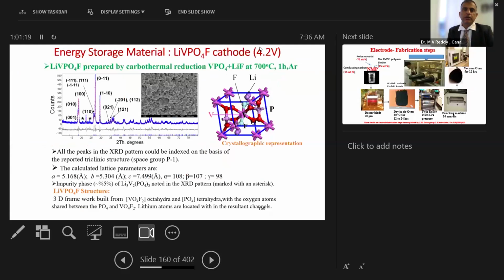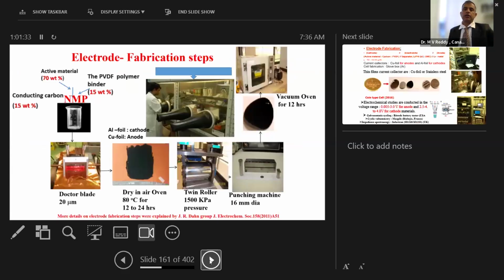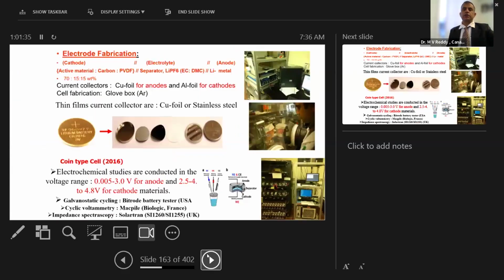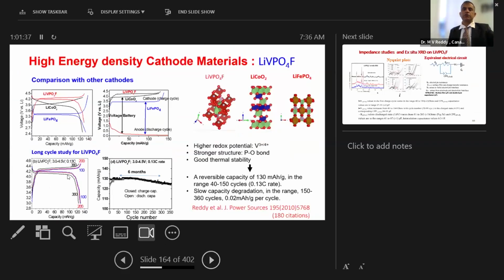So typically you get a 4.2 volt cathode material. I told you that there is VPO4 LiF, finally 700 degrees, 1 hour, and argon. So the X-ray is the one to tell the single phase material. We characterize them, make sure that they are reasonable, and fabricate them, and then finally the similar button cell approach.